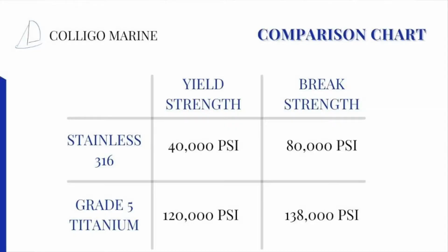Now, what we do at Colligo is we do not make the sections smaller. Even though titanium is much stronger than 316 stainless steel, the problem is 316 stainless steel starts bending. The yield strength is about 40,000 psi, but it doesn't break until 80,000 psi. So you've got a big window of opportunity to overload it. The piece bends, but it does not break, so it's not a bad material for a structural component on a